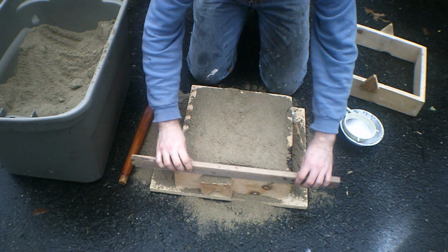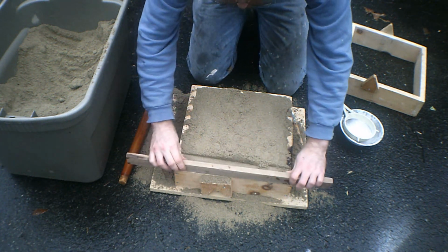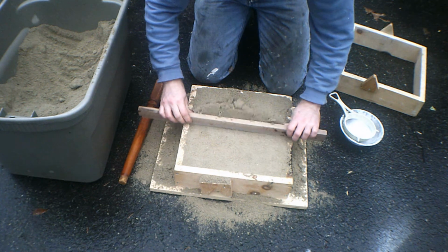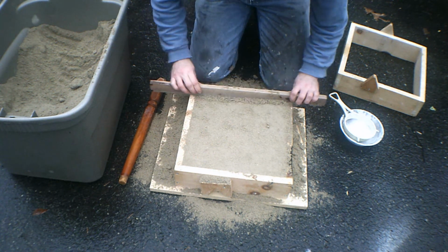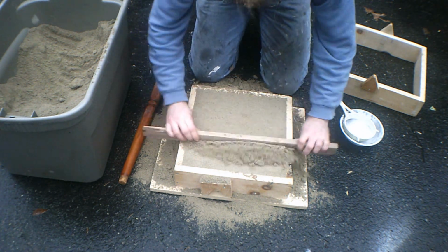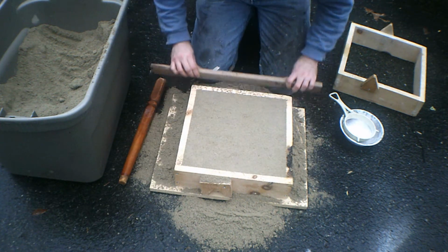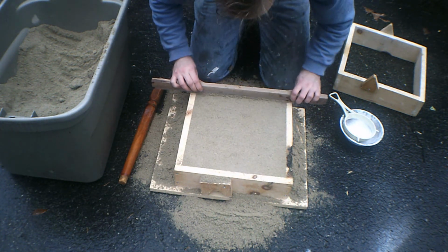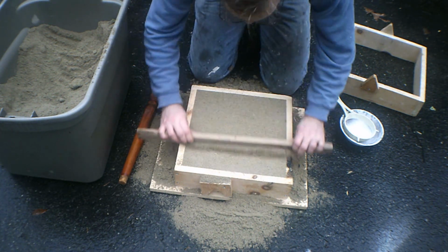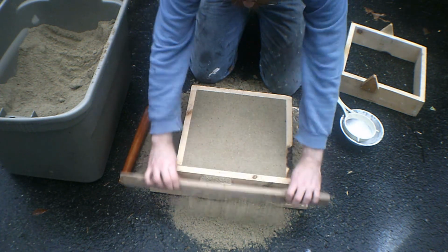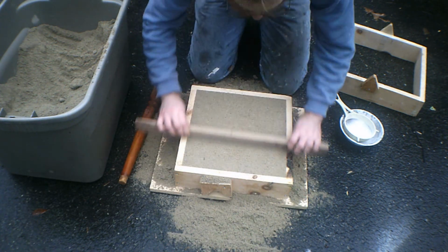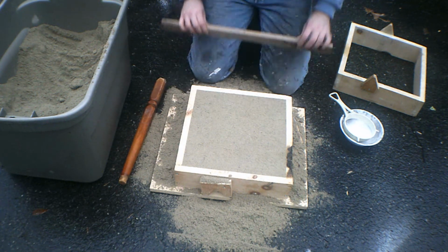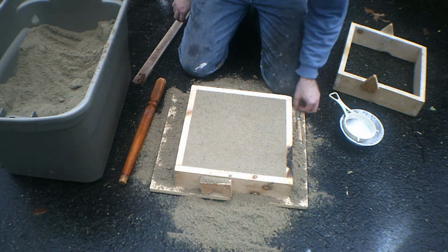For the final strike off, you're looking for a completely flat surface on the bottom. So I go back and forth a few times and I make a sawing motion with the stick to get a flat surface as much as possible. Now that makes little bits of sand on the edges stick. So going back and forth is key to actually getting a surface that is flush with the bottom of the flask. That way when you roll it over, it won't collapse at all.